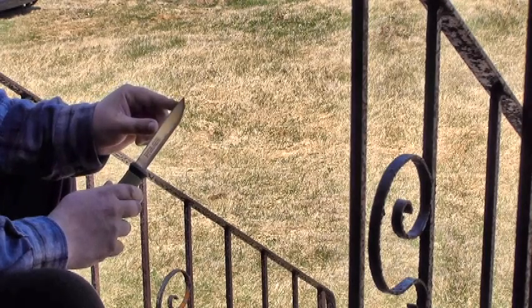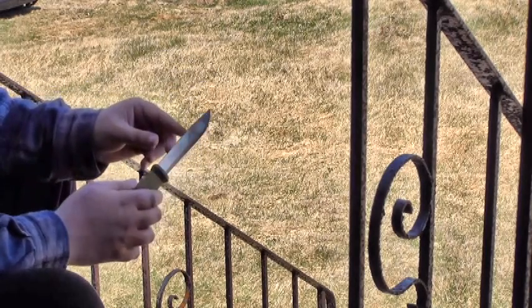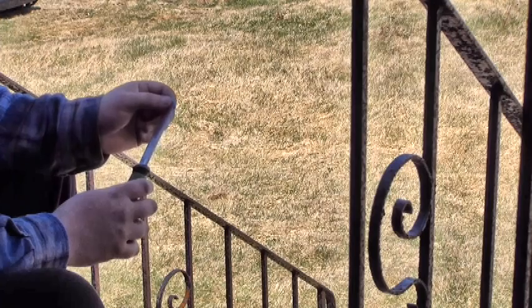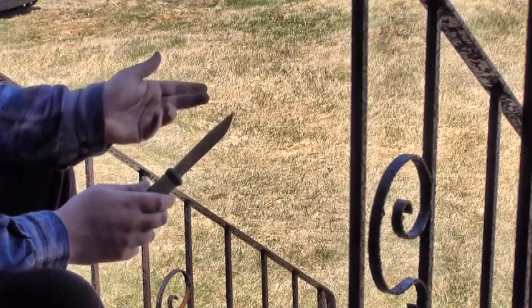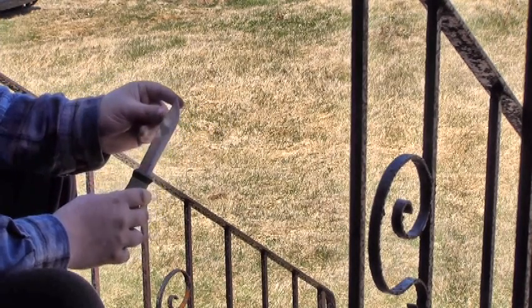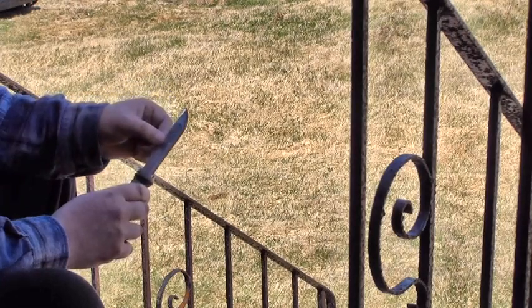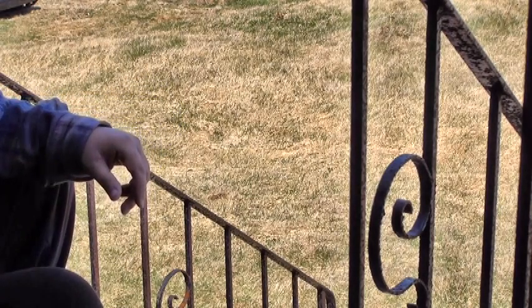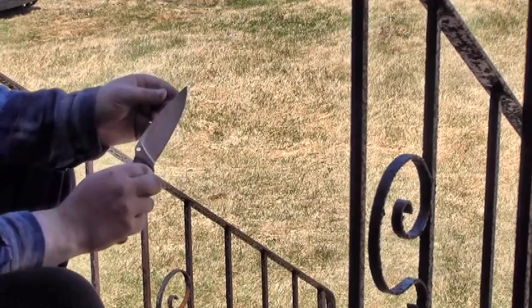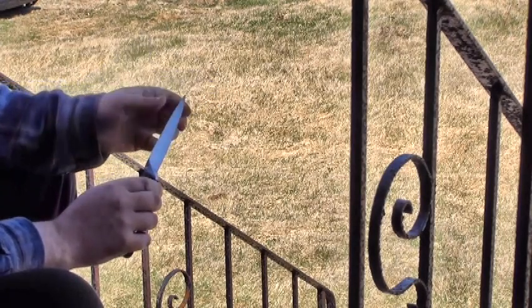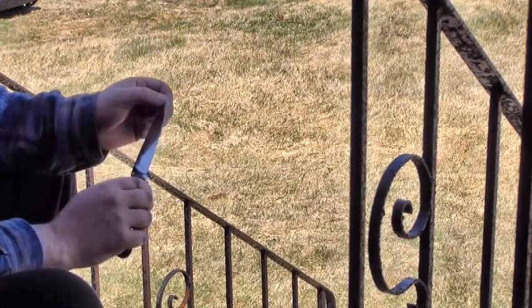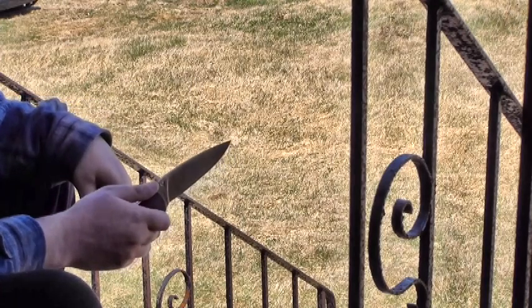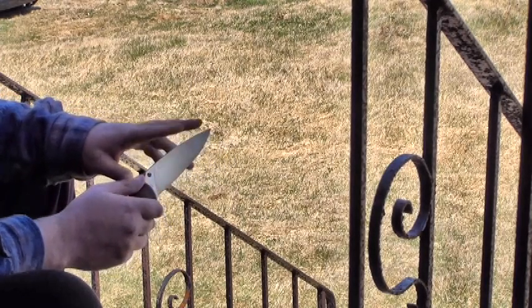So for example, while I would rigorously pry thicker barks off with the Mora 2000, and in the case I do eventually end up overloading it, you will just put a slight bend in the tip of the blade. But if you start doing heavier work like that with a high carbide steel, at some point you'll just crack a piece off the tip with very little warning. So that's one of the downsides to the higher carbide steels.